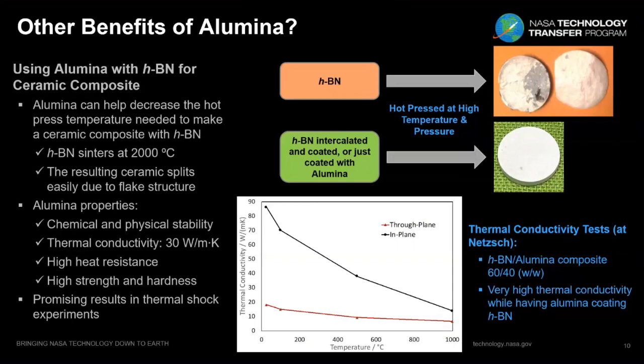And when we were finally able to make the puck that we needed, it just broke because of the shearing properties of hexagonal boron nitride. And so by adding alumina, by intercalating and coating or just coating hBN, we can decrease the sintering temperature and make a more robust ceramic composite, like the one that I'm showing here in the picture.